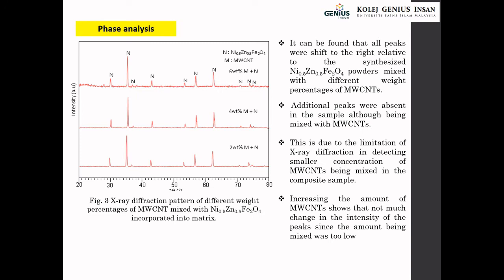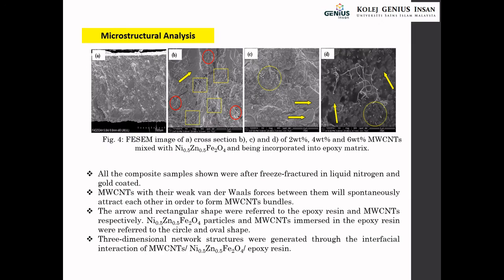For the next phase analysis, we mix MWCNT and nickel zinc ferrite with different weight percentages from 2 weight percent until 6 weight percent. It can be found that all peaks were shifted to the right relative to the synthesized nickel zinc ferrite powders mixed with different weight percentages of MWCNTs. Additional peaks were absent in the sample although being mixed with MWCNTs. This is due to the limitation of X-ray diffraction in detecting smaller concentrations of MWCNTs mixed in the composite sample. Increasing the amount of MWCNT shows not much change in the intensity of the peak since the amount being mixed was too low. We mix until 6% since beyond it will not produce an optimized result for our electromagnetic wave absorbing materials.